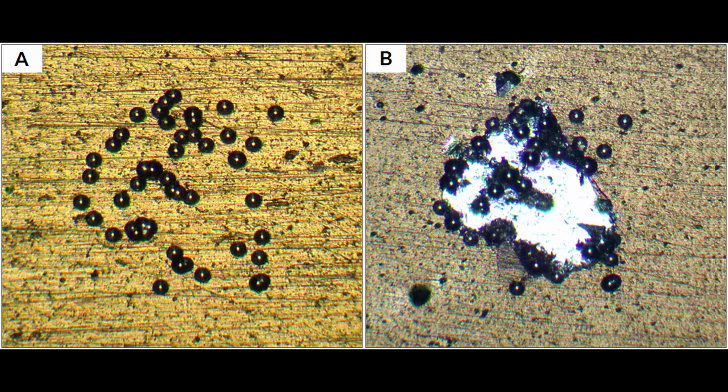Here's another example of two multilayered nitride coatings, which illustrates the sensitivity of this test to coating performance under high strain rate impact across a defined area. The two samples were subjected to 50 1-newton impacts across a 400 by 400 micrometer area. Extensive coating failure is observed for coating B, in contrast to coating A, which does not show any failure despite both coatings having very similar hardness and elastic modulus.